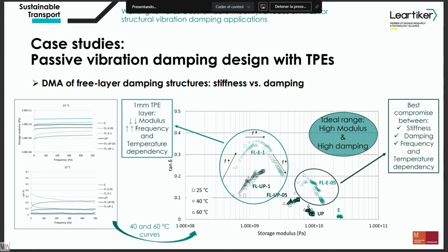So in that case, for example, if we compare the different structures with different thicknesses, for example, the free layer epoxy with 1 millimeter, if we compare it with free layer epoxy 0.5, we can see that with increasing the thickness of the TPE layer, the modulus is decreased and we have a higher dependency with the frequency and temperature. So it's more dependent on the frequency and temperature, so more viscoelastic.